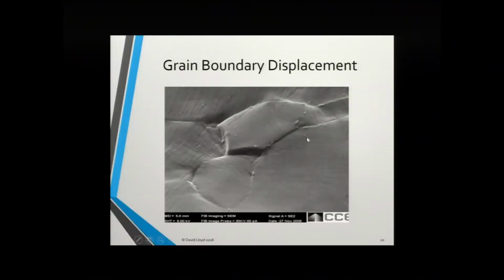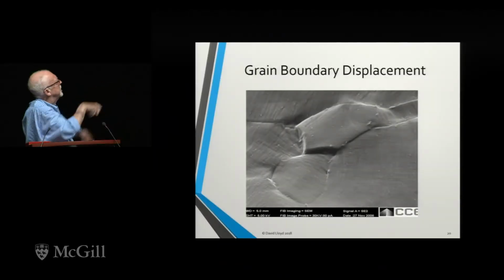Again, this is a 55-degree angle. This is a displacement at the grain boundaries, and you can see the slip lines going on inside the grains. And some of these displacements are really quite sharp, and if you look at them at higher magnifications, along this displaced surface you'll actually see evidence of slip lines on that as well. So as this grain is doing that, general plasticity is also occurring in the grains.